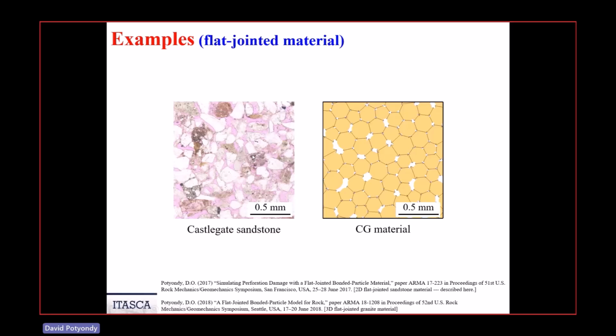This is Castlegate sandstone. This is the cross section. You can see the length scale here. The pink is basically void space between the grains. Here is a flat jointed material that has the disc size at the same scale as the grain size of this Castlegate sandstone. Obviously, this is a much simplified representation, but let's just see what we can get with it. This, by the way, is the work that I did for BP, where we looked at perforation damage. The first part of that work was to see how well the flat jointed material, which I had just developed, behaves.